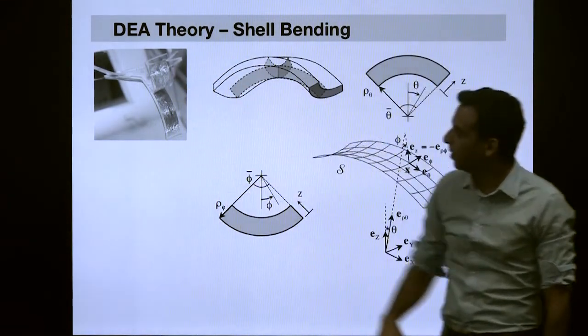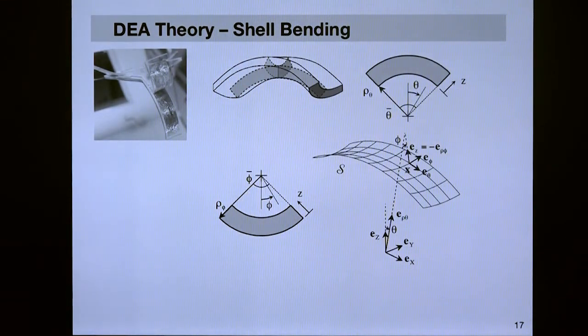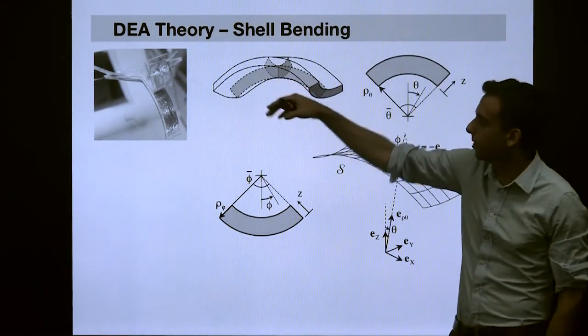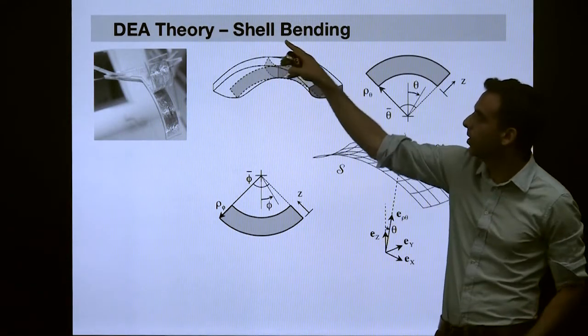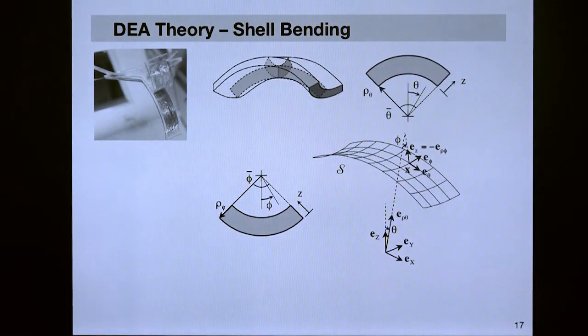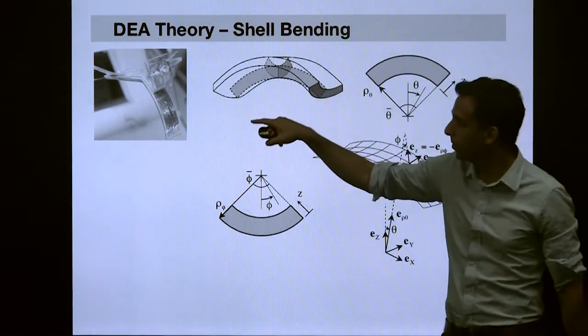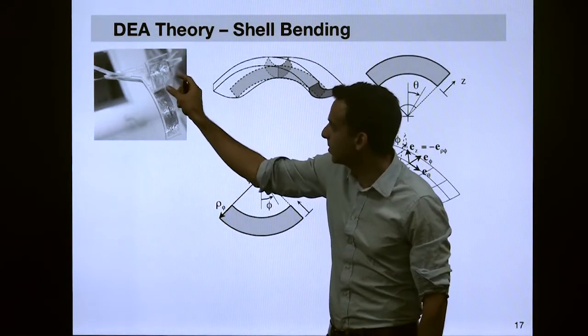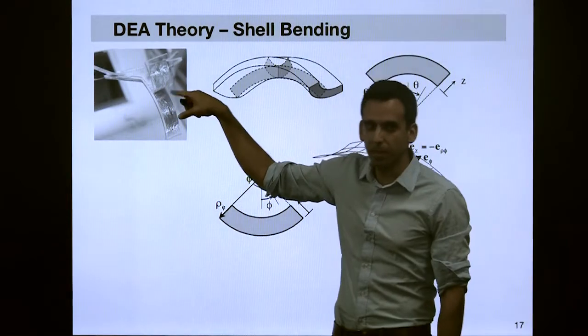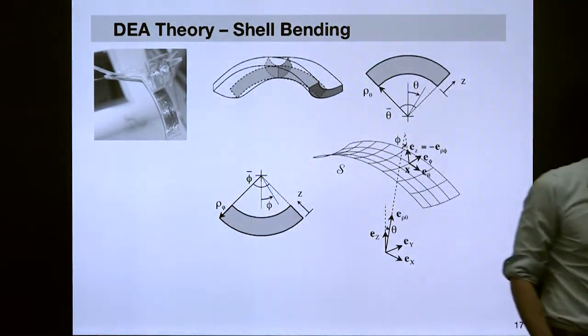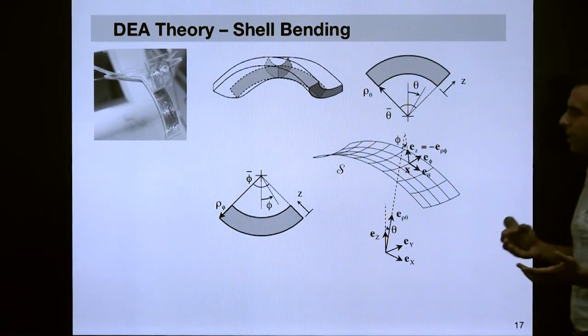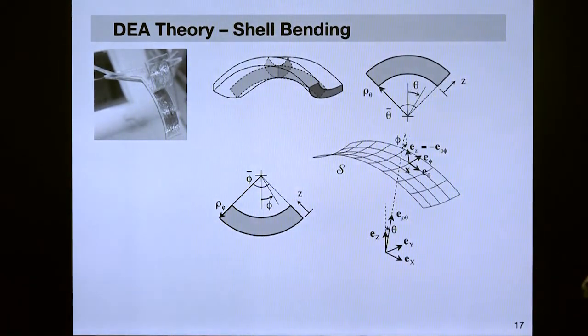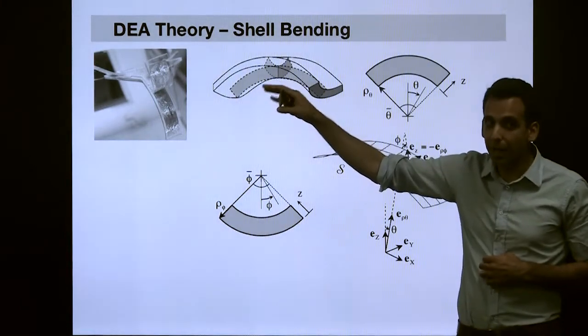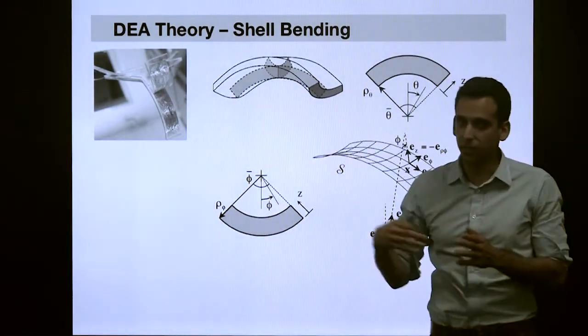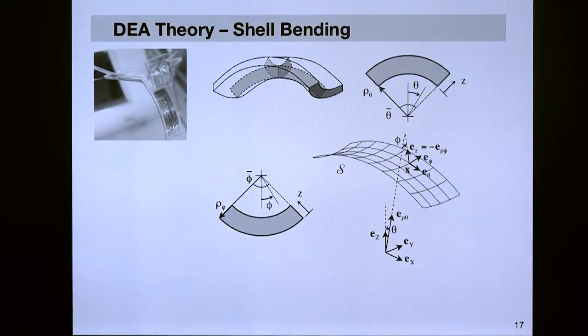It was probably clear from the other pictures, but if you look at the actual stable geometry of these dielectric elastomers carefully, you'll find that instead of just undergoing pure bending, it's actually undergoing this shell-like deformation where we have negative Gaussian curvature. We have two principal curvatures, one along this principal bending axis, but along the width, we also have some slight amount of bending curvature, but in the opposite direction. The first pass would be just to ignore that second principal curvature, except it turns out that it can potentially have a very big role in establishing that electromechanical coupling between applied voltage and bending curvature.